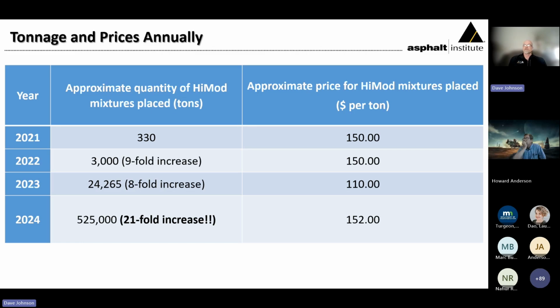That first project was that 330 tons that was placed at the Wendover facility at $150 a ton. In 2022, there was an increase of tonnage of about a 9-fold increase to 3,000 tons, again at that same unit cost. Then in 2023, there was another 8-fold increase, a bit over 24,000 tons in some different applications. And we saw that the cost per ton went down as the industry became more comfortable with this. The price went down, as well as that higher volume of material. The one asphalt producer in particular was very aggressive in their pricing to attempt to be successful on those projects with their contractor colleagues.